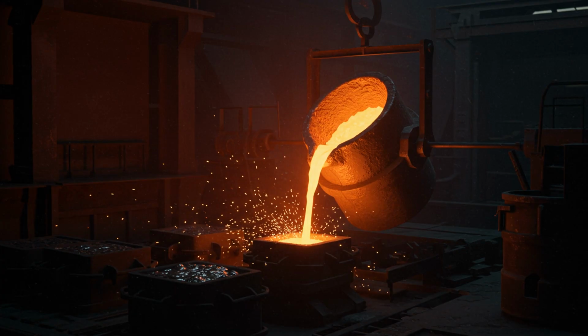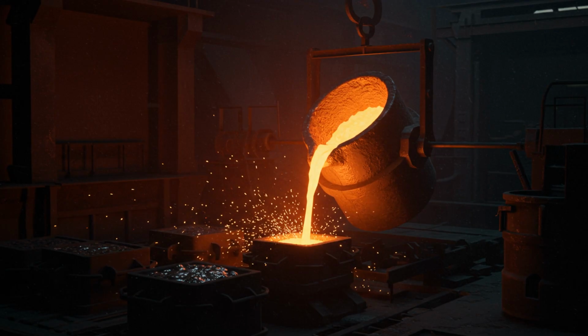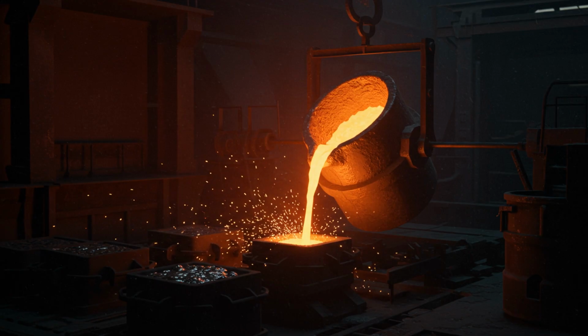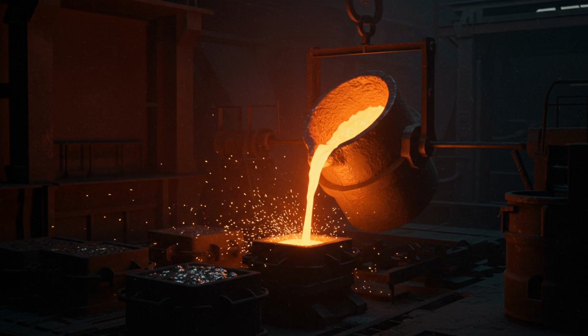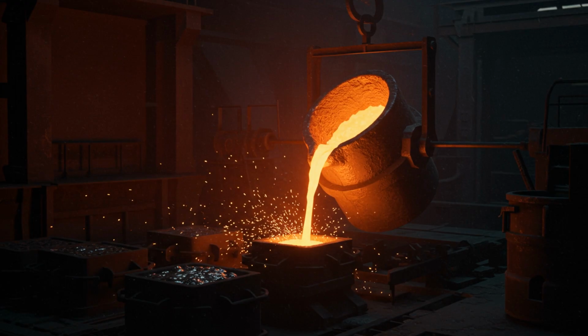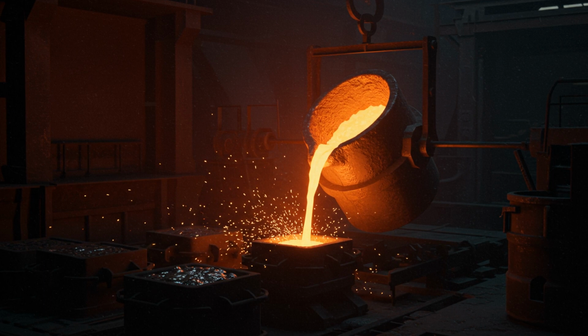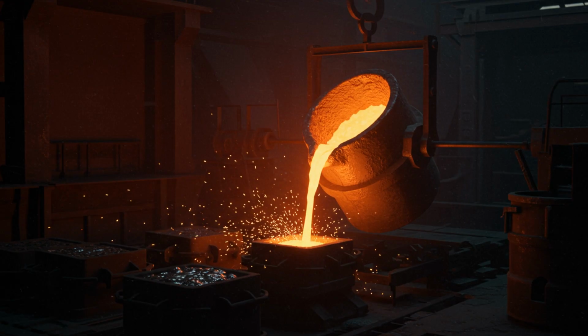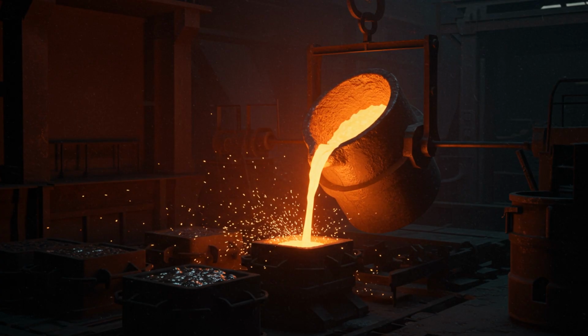It all begins with chemistry, because ordinary steel, or even titanium, would soften and fail within seconds inside the high-pressure turbine. Engineers turn to nickel-based superalloys, materials engineered at the atomic level to resist creep, which is the tendency of a solid material to move slowly or deform under mechanical stress. These alloys are a precise cocktail of nickel, cobalt, and rare earth elements like rhenium and ruthenium. Rhenium is one of the rarest elements on Earth, added to prevent the metal from losing its shape at extreme temperatures. These raw materials are melted in a vacuum induction furnace to prevent any contamination from oxygen.